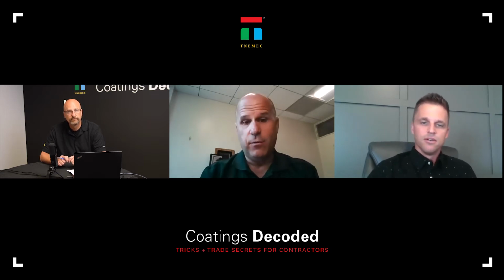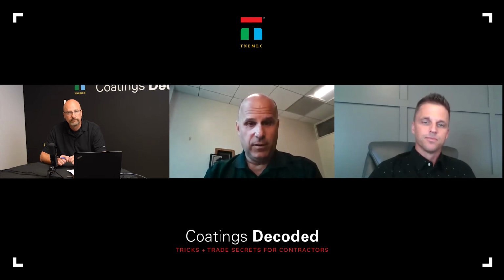That's exactly right. So in your example, with a difference of 2, you would need half the thickness with the lower thermal conductivity material to achieve the same total insulation value, or R-value, in your insulation system. And so with all manufacturers pretty much listing thermal conductivity on their data sheets, it's a really quick reference for contractors, architects, or owners to quickly gauge which product is going to be most efficient for their need.